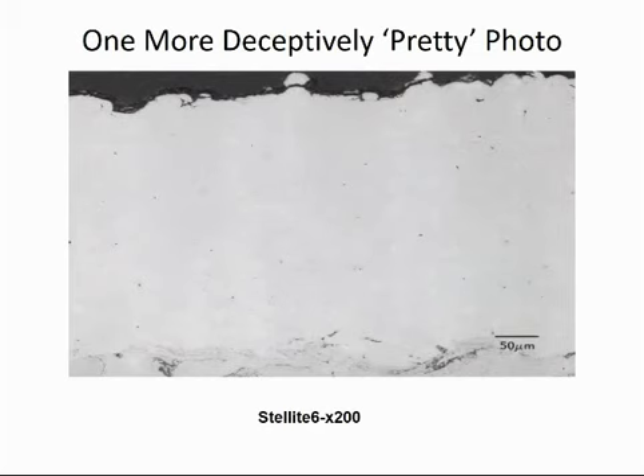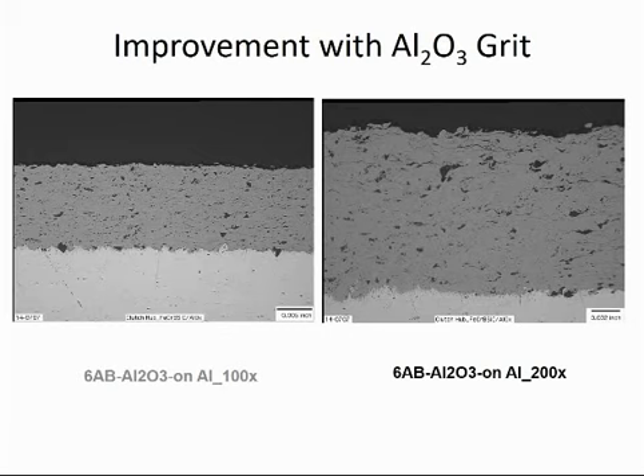And here's another pretty picture that had the same kind of problem. Here we have the improvement that's gained by adding aluminum oxide to the coating. As you can see, it makes it difficult to gauge the porosity in the coating, but the density is much higher. Junk is removed by the blasting effect, and the blasting effect makes for much better intimacy between the particles that build up the coating. So although you can't gauge the porosity very well in a photomicrograph, our gas permeability tester allows us to see that nothing's getting through this coating. It's actually quite tight.